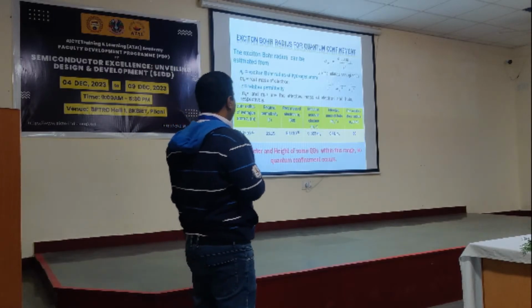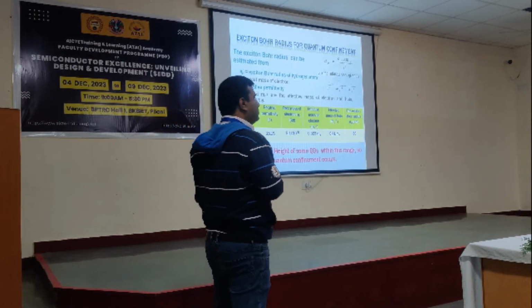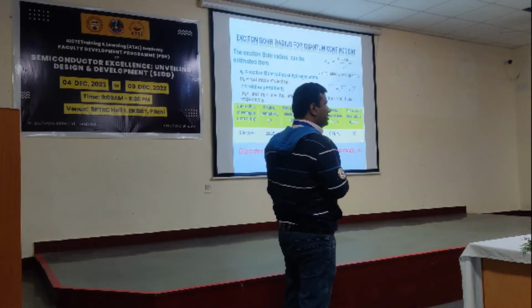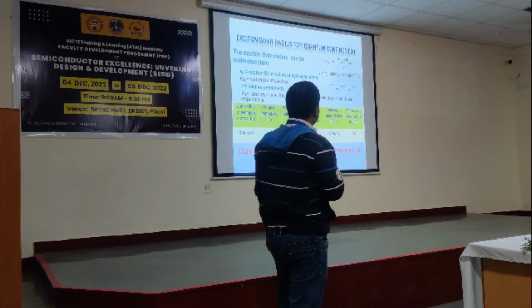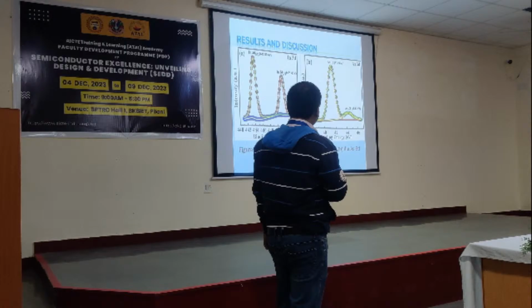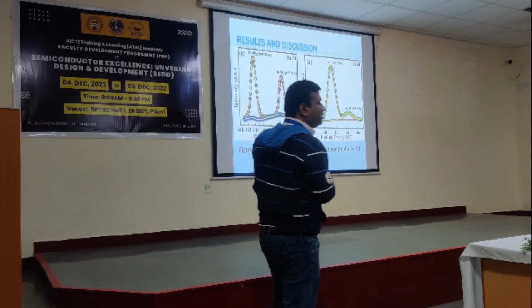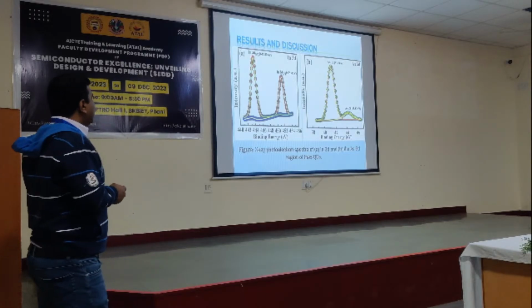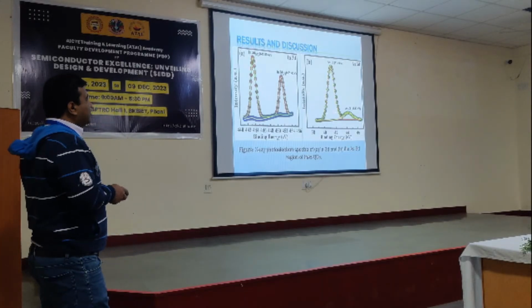In our previous cases you have seen the size of the particle in the range of 5 to 18 nanometer, which is much less than 36 nanometer, so you can say that the formation of quantum dots actually happened. Now, to ensure the formation of the material, in our case indium arsenide, indium will be present and arsenic will also be present.